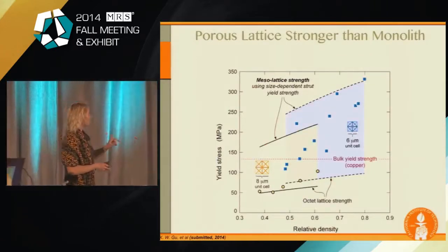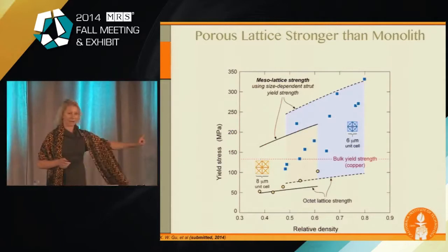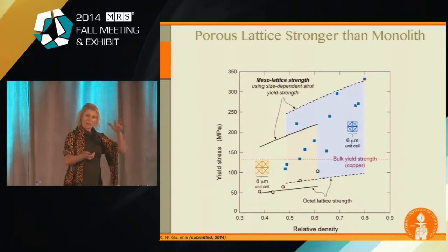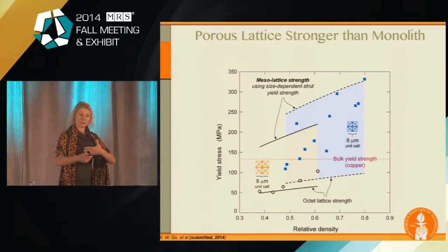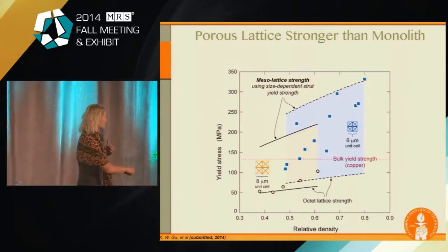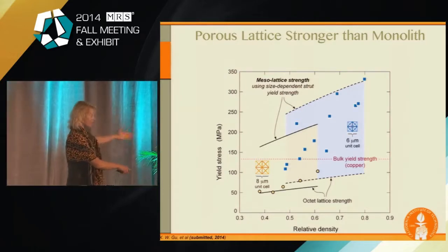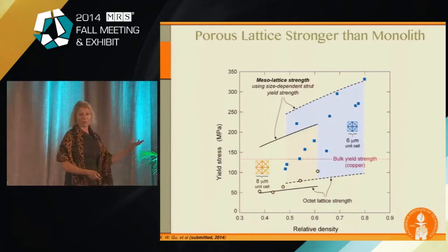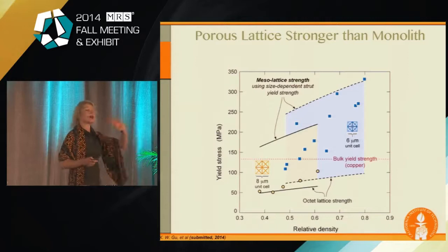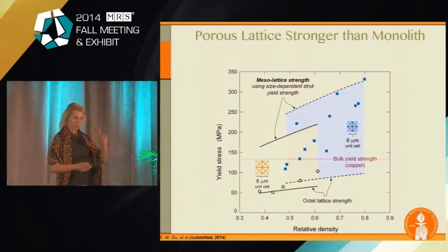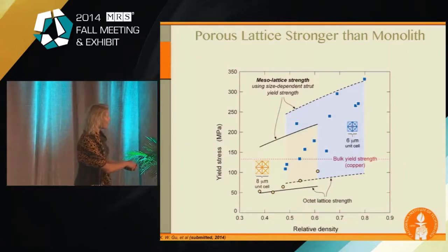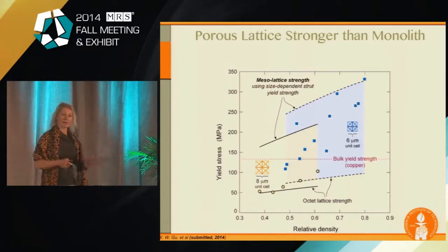And this is actually a pretty neat manifestation of a size effect. I'll walk you through this. Imagine a monolithic cube of copper, okay? And if you measure its strength, it would be somewhere over here. So this is strength as a function of relative density. And now these are pretty dense structures. So we're going from about 30, maybe 40% up to 80%. So these are not 99% air. They're much denser structures. But here's what happens. If you take a monolithic cube of copper, it'll be here somewhere. So it's about 120, 130 MPa, right?